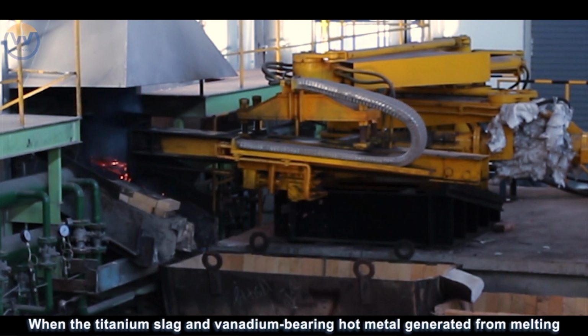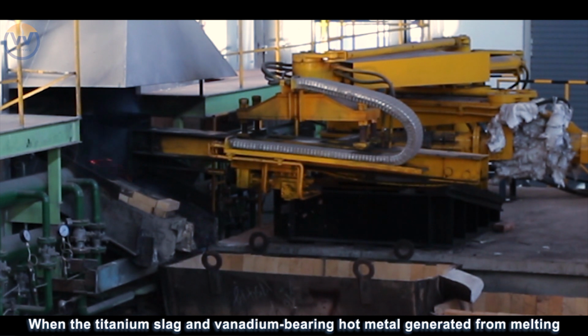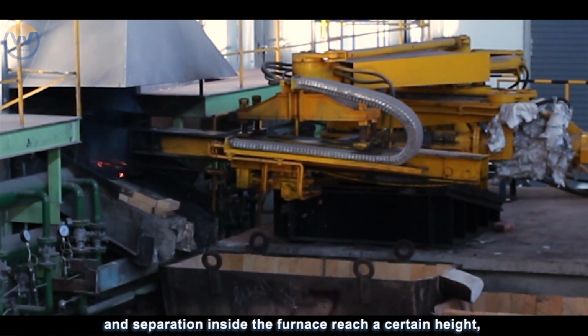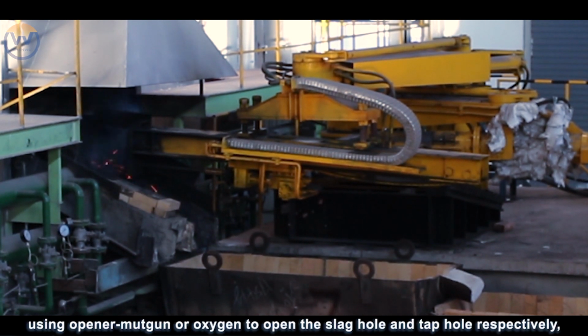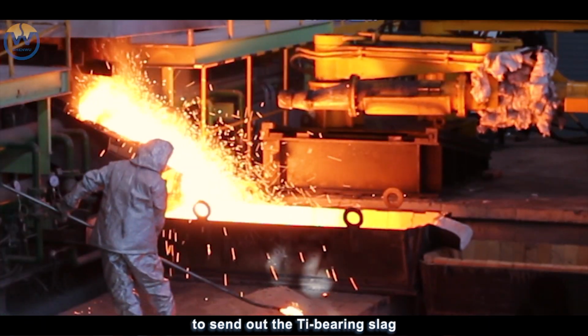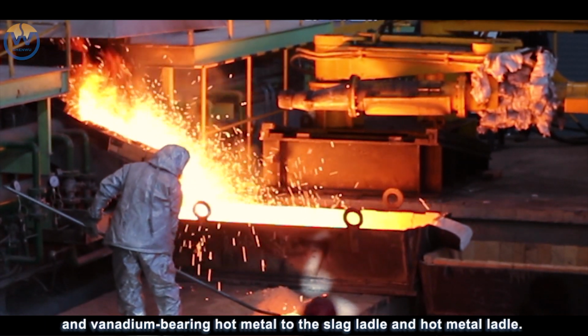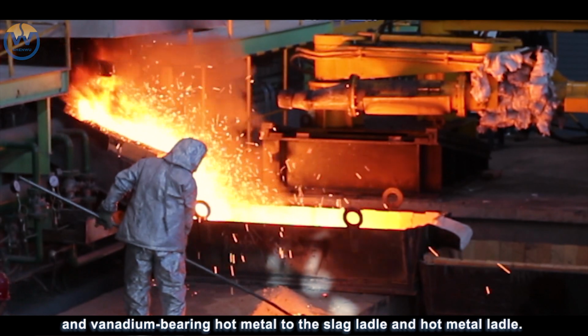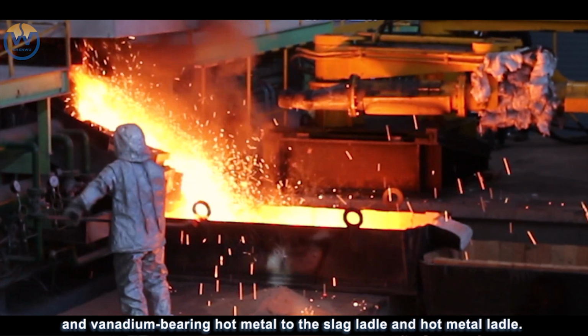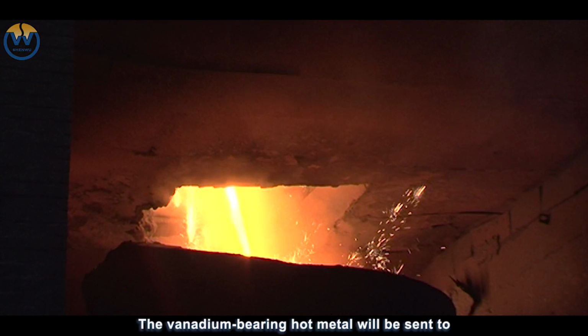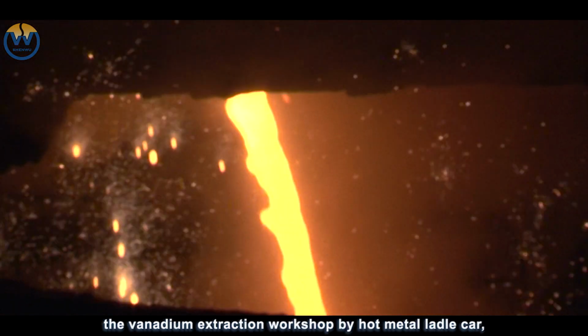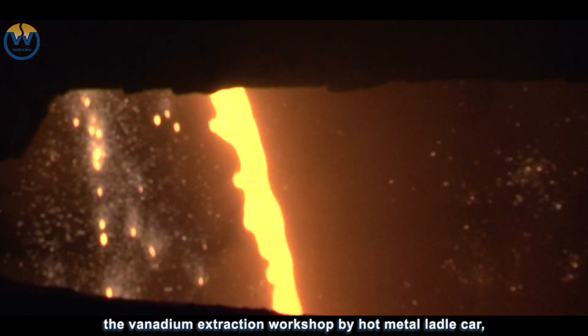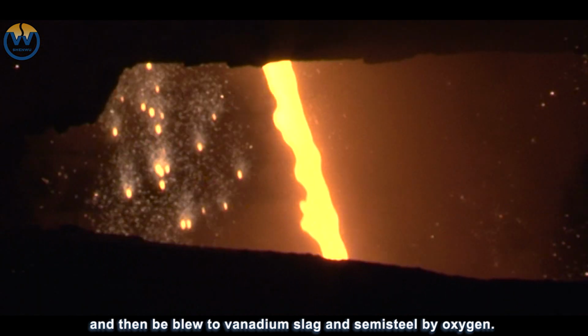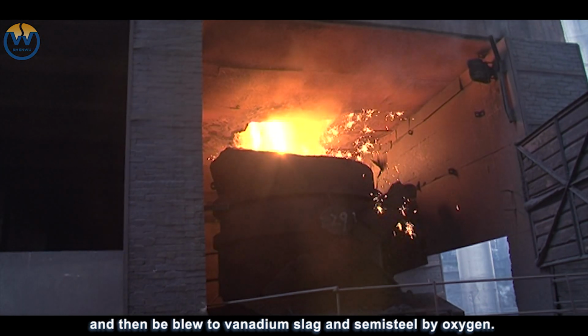When the titanium slag and vanadium bearing hot metal generated from melting and separation inside the furnace reach a certain height, using opener mud gun or oxygen to open the slag hole and tap hole respectively to send out the Ti bearing slag and vanadium bearing hot metal to the slag ladle and hot metal ladle. The vanadium bearing hot metal will be sent to the vanadium extraction workshop by hot metal ladle car, and then be blown to vanadium slag and semi-steel by oxygen.